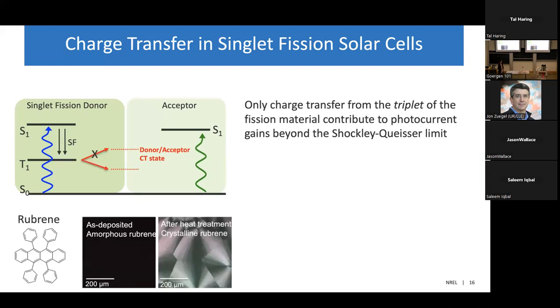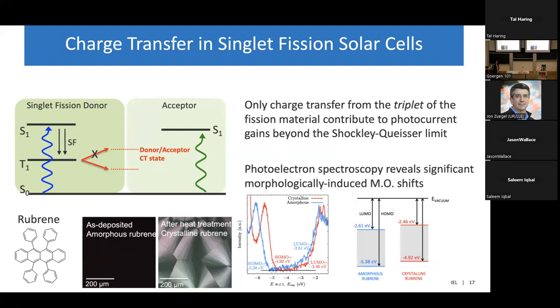So first we studied a singlet fission semiconductor called rubrene. It's this tetracene derivative that has 4 phenyl groups hanging off of it. And my colleague Mike Fusella found that with a fairly simple heat treatment, you could transform as-deposited amorphous rubrene films into this nice crystalline morphology. And when we look at the molecular orbital levels associated with these 2 different films, we see pretty significant differences of a couple of 100 meV in the 2 different systems.